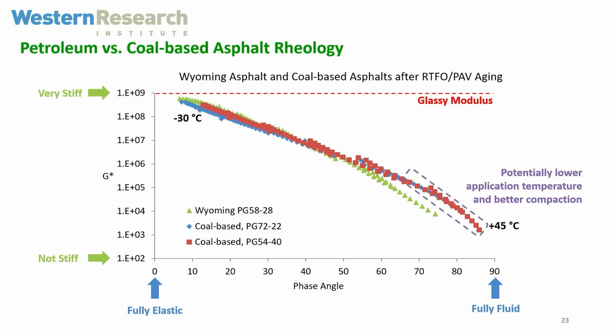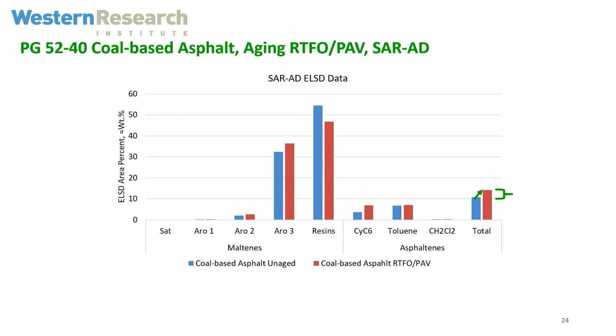The other thing that is interesting is that these materials become a little bit softer, a little bit more fluid as you heat them up. We don't know for sure, but this may have additional benefits. This could lower the paving temperature, which is a big issue in the industry because they're trying to lower their carbon footprint on the building of the roads. And you could get better compaction because when you make a road, they go over it with the steam rollers for a reason. They got to compact it and get at the air voids because that can cause some issues with oxidation, with moisture, and all kinds of things. So there could be additional benefits to this material.